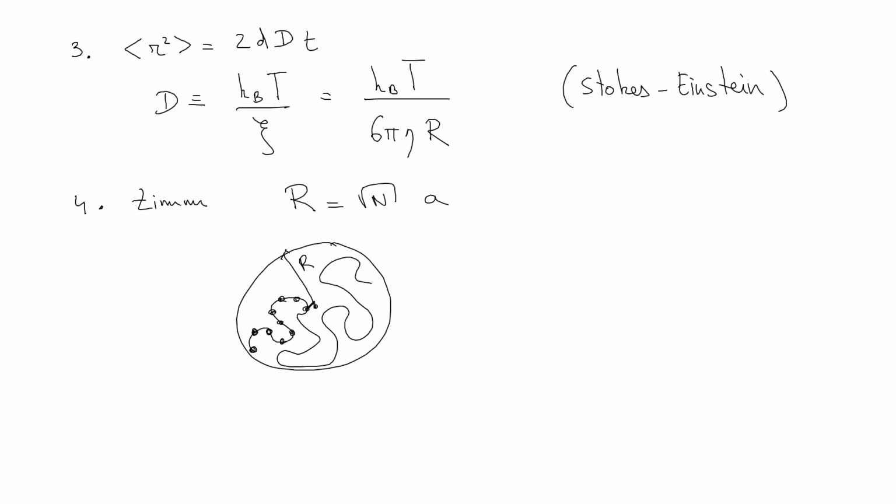And you see what I mean. So for the Zimm situation, it has been proposed that, in fact, this moves in a solvent at a certain velocity, and the solvent goes around inside. Basically, the solvent is moving together with the monomers, and so this is acting as a hard sphere, as a rigid object. There is no fluid motion inside the polymer chain. That's one assumption. We could discuss it later.